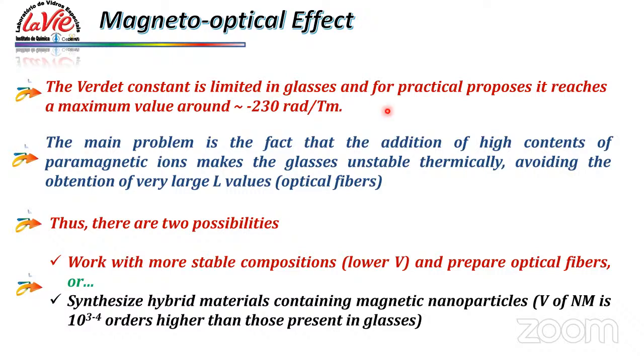So the main problem is the fact that the addition of high contents of paramagnetic ions usually makes the glass thermally unstable. So it will avoid, for example, the obtention of a very large length, for example, if you intend to have optical fibers. So we must have a compromise here between the amount of ions, the glass composition, and the thermal stability that we can reach with this glass.